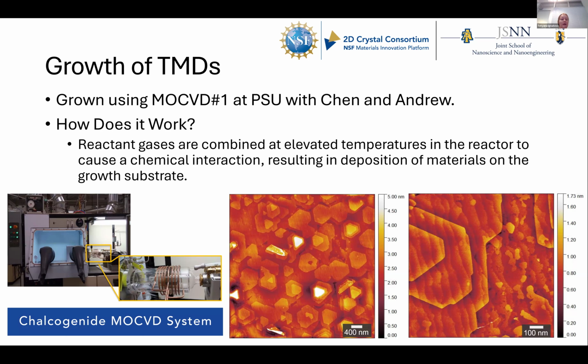In case you do not know how MOCVD works, I wrote a little description saying that the reactant gases are combined at elevated temperatures in the reactor to cause a chemical reaction. During that chemical reaction, they form a layer of material on your growth substrate. On the right are two AFM images of grown MoS2 using MOCVD. As you can see, they're multi-layer, and some areas are coalesced and everything is beautiful.